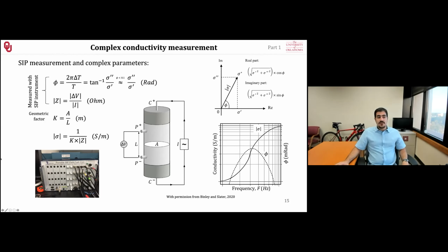So as I said, you will be measuring a phase lag, which is basically the inverse tangent of the imaginary part, or the energy storage, over the real conductivity, or energy loss. Because at the lower frequencies these are very different from each other, we can just ignore the tangent, or simply put, the phase would become the imaginary conductivity over the real conductivity. And it is measured in radians, but in reality, for environmental applications, that's much smaller than radians, and we get